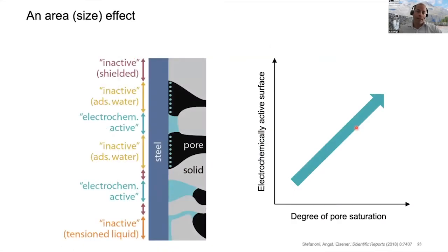To understand that, there is the theory of a size effect, actually an area effect. Again, the steel is in contact with solid phases and with pore space, and some of the pore space may be filled with liquid and some not. Of course, if we increase the amount of surface where we have a bulk liquid electrolyte present, we do that if we increase the degree of pore saturation. So that means an increase in electrochemically active surface area, and therefore also an increase in apparent macroscopic corrosion current density.